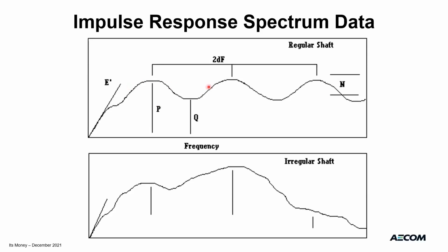The mean height of the curve is a function of the cross-section area and the concrete density. The upper and lower bounds are marked here for typical upper and lower range of concrete quality. If the concrete is less dense than expected, this curve will rise. If it's more dense, the curve will be lower. Likewise, cross-section. If the cross-section is oversized, the mean amplitude will be low. If it's undersized, it will be high. So all that information can come out of a good test result. Even in complex irregular shafts, we still get more information than we would expect to get from an echo test.